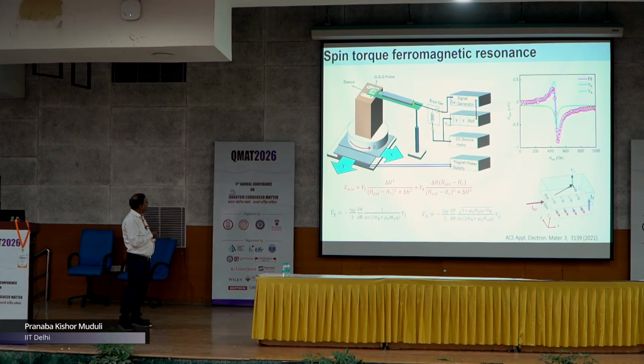In our lab we have this spin torque ferromagnetic resonance technique where we apply a microwave current instead of a microwave field, and then we get this resonance curve. From this you can fit the symmetric and anti-symmetric line shapes. The symmetric is related to the in plane torque, and the anti-symmetric is related to the out of plane torque. This is very broadly speaking, but it's actually much more complex. So we wanted to do that measurement.